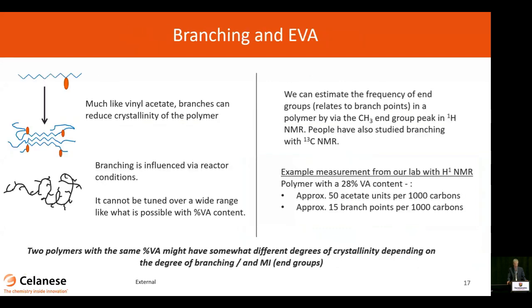So first, let's talk about branching in general. Here, when I'm talking about branching, the majority of the branching in the polymer is going to be short chain branching, but there is some long chain branching that'll come up in this number as well. So first of all, much like vinyl acetate, these branches are bulky side groups that don't readily incorporate into polymer crystals. So much like the effect of vinyl acetate, increasing the amount of branching in the polymer is going to suppress the crystallinity of the polymer. Now, the thing is we can tune the amount of branching in the polymer a little bit.